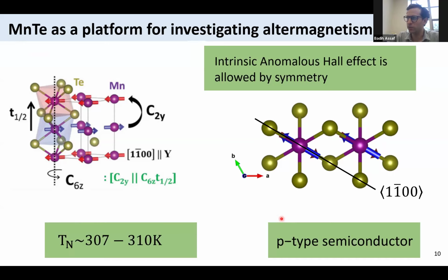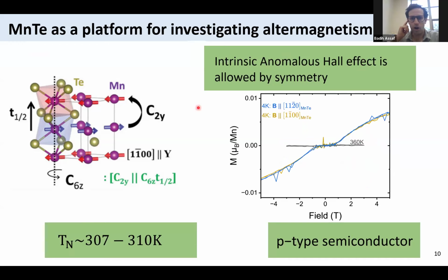And the analysis of the symmetry of this material has also revealed that the anomalous Hall effect is allowed in it as long as the magnetic easy axis is along this 1, 1 bar, 0, 0 direction. All of this happens, so this intrinsic anomalous Hall happens despite the fact that the magnetization is tiny in this material. This is an actual measurement.